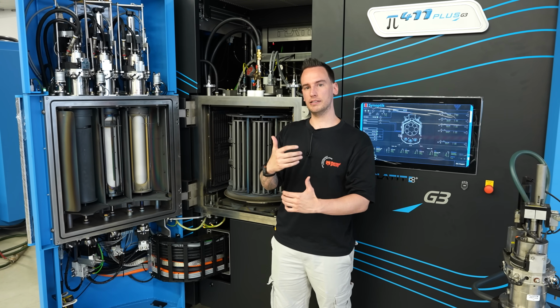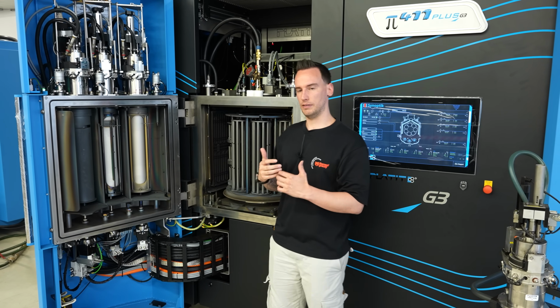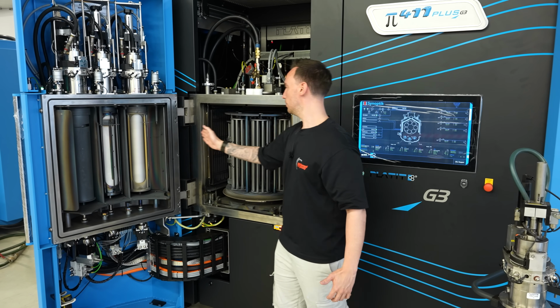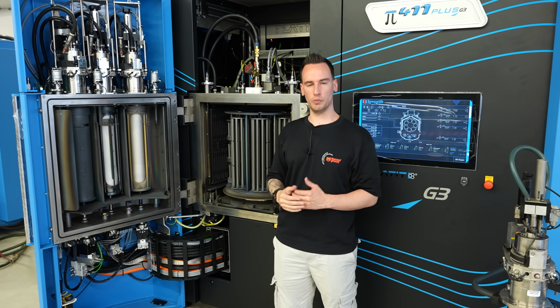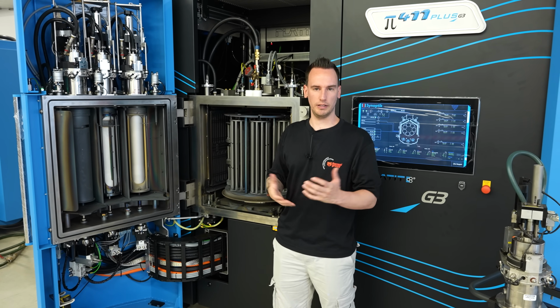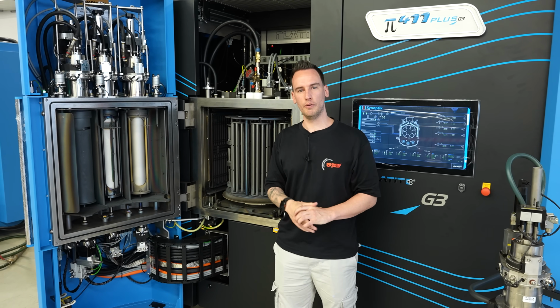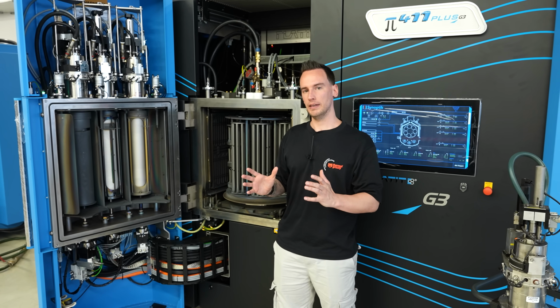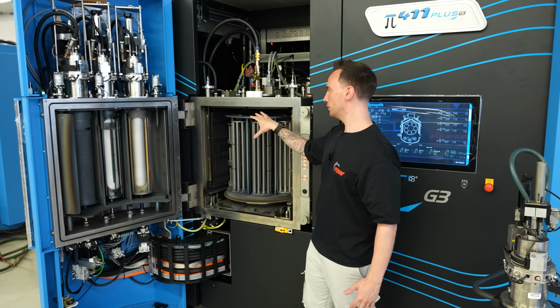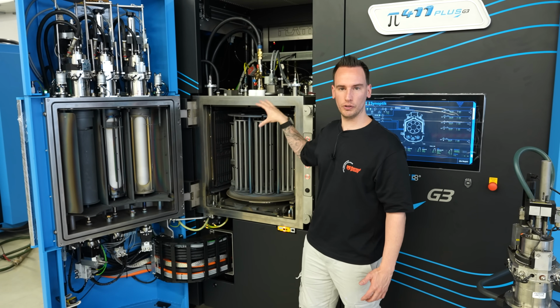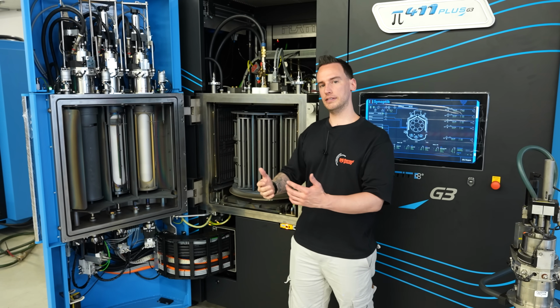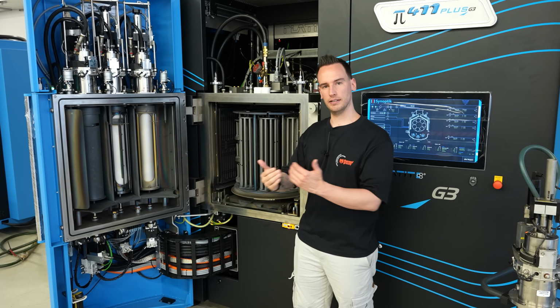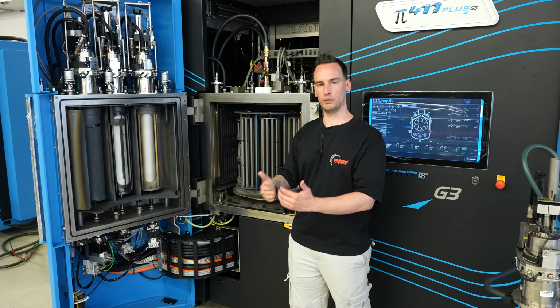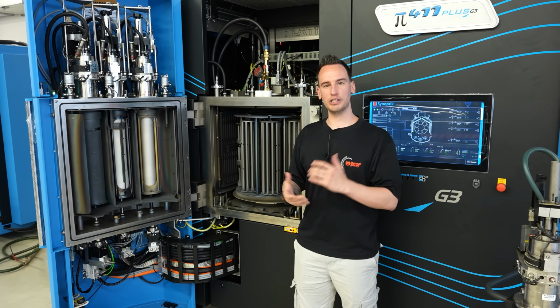By doing that, it's releasing the metal ions, and the metal ions can then flow almost freely towards the material you want to coat, like in our case, a 5090 cooling block, where you want to create a nice coating. In addition, you have a bias voltage onto the carousel, and this voltage is basically attracting the metal ions from the cathode towards the material. And that's how you then create your coating.